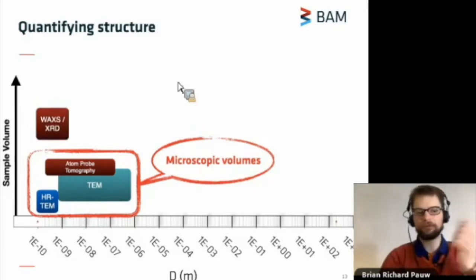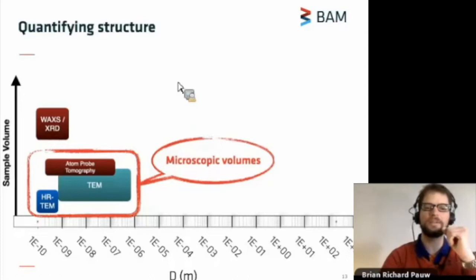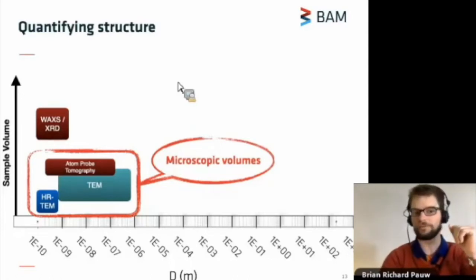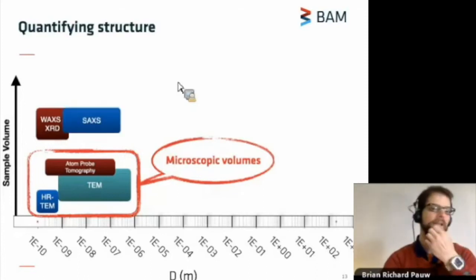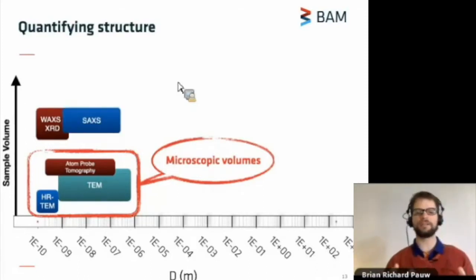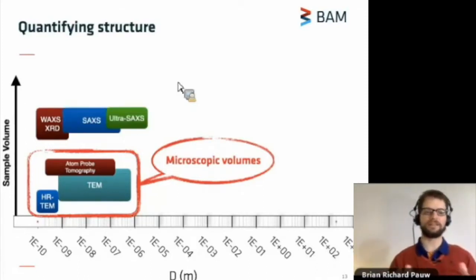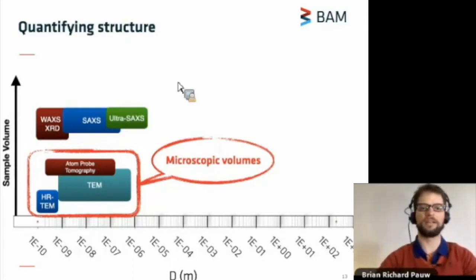The techniques of X-ray scattering come in three variants. They're all the same, I think. Well, they're all based on the same principle. This is wide-angle X-ray scattering, small-angle X-ray scattering, and ultra-small-angle X-ray scattering. These differ a little bit in the size range that you're analyzing. So, with the combination of these three, you can characterize or quantify the structure over the size range of angstroms to microns.